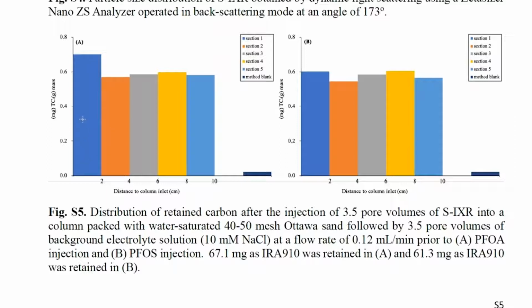So this shows you the distribution of the carbon with distance, and you can see it's quite uniform across the length of the column. And this is what we want. We don't want a whole bunch in the front and then it drops down. So sometimes when you see particle distribution curves, you get a lot of attachment right near the inlet and then it drops way down. And this shows that we get a very uniform distribution of basically the beads within the porous medium.